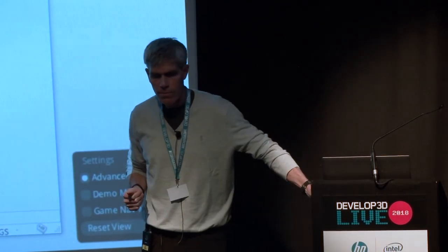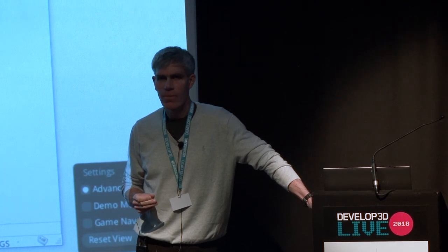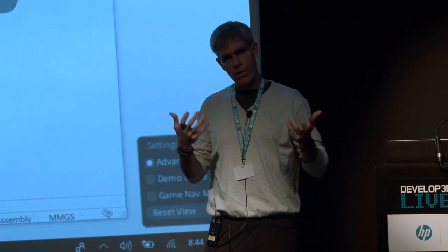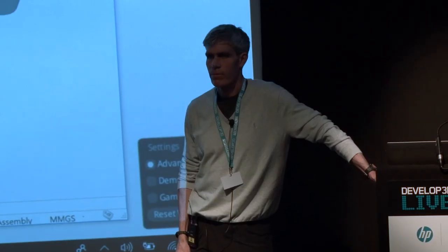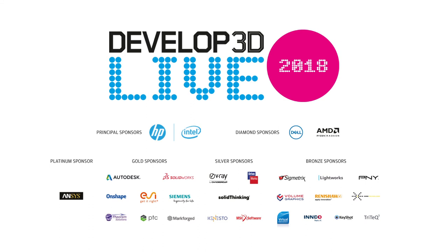I think we're out of time, but you can certainly come up afterwards with questions or comments. Question from audience: What is the quality of the final printed metal parts on a density basis? Answer: It's at least 98%, so we're getting very, very good results. It's very similar to what you get with metal injection molding — all the materials are qualified and the process is well known. Metal injection molding has been around for years: you make a mold, squish the material in, de-bind it, and sinter it. We have the same types of results as that industry.